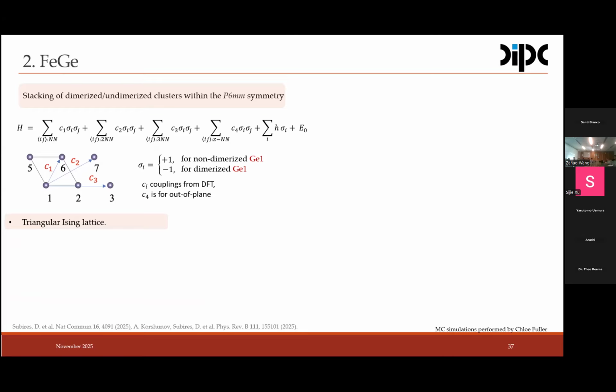And we can map this frustration by assuming an Ising model, an Ising Hamiltonian, where we give the isospin values of ±1 to dimerized germanium and non-dimerized germanium. This is the Ising Hamiltonian, where sigma i and sigma j are the spins, and C1 and C2 are just strain parameters, which account for the coupling between the dimerized and non-dimerized germaniums. I have to say that in this model, we only consider the germaniums. We get rid of all the rest of the atoms. We don't consider iron at all, so there is no magnetism here.